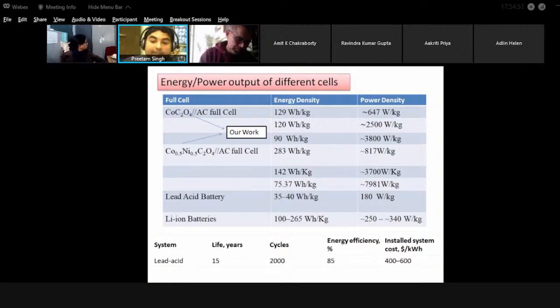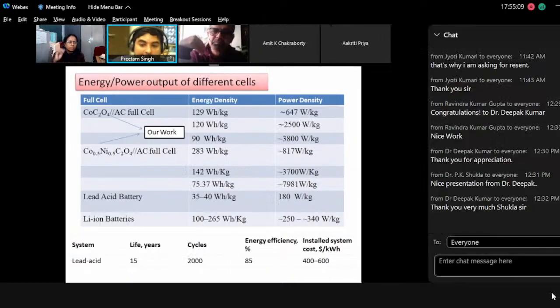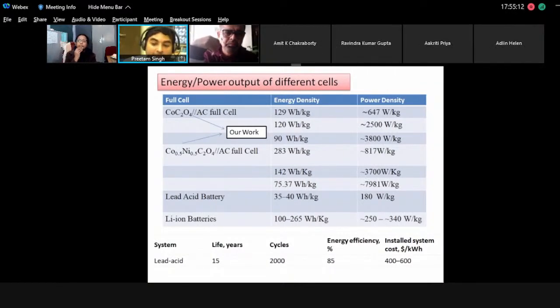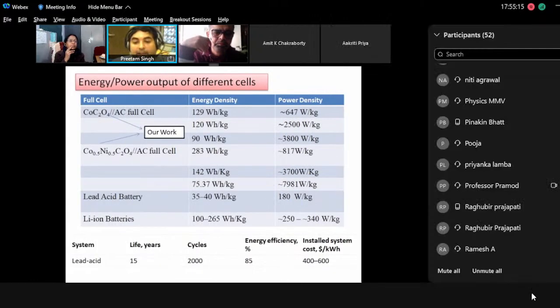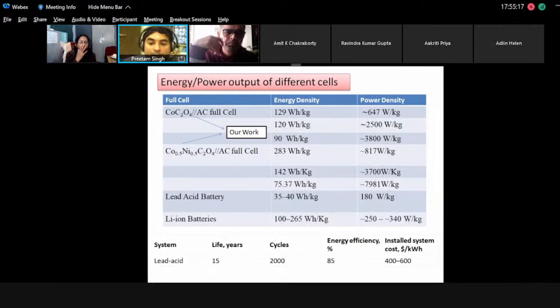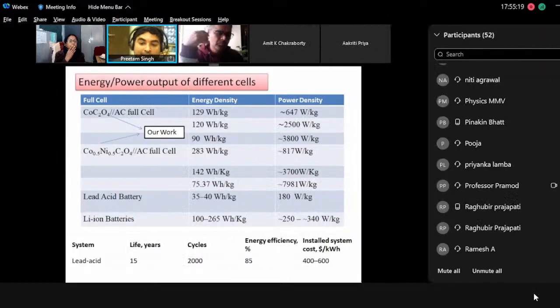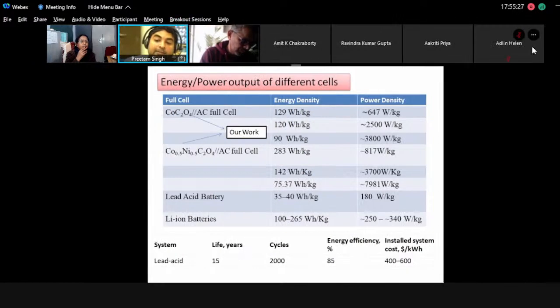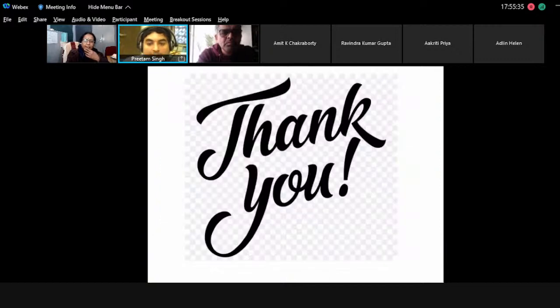So see, the new materials, especially structured materials and structural designs, can lead us to grid storage bulk energy devices. Now it's not only that we have made a single electrode test, we have done a full scale test, which is showing very, very promising results, at least for the replacement of lead acid batteries. So the takeaway of the talk is that the new materials are very important, especially framework structured materials. Much better things can be offered, especially transition metal oxide, transition metal ion based framework structures that can do the redox, and whose porosity can give very high energy density. So that's all from this talk from my side.